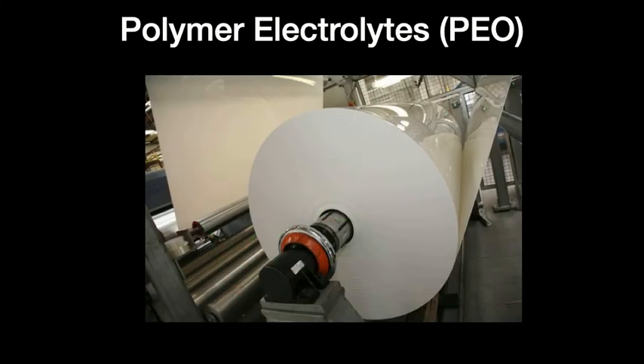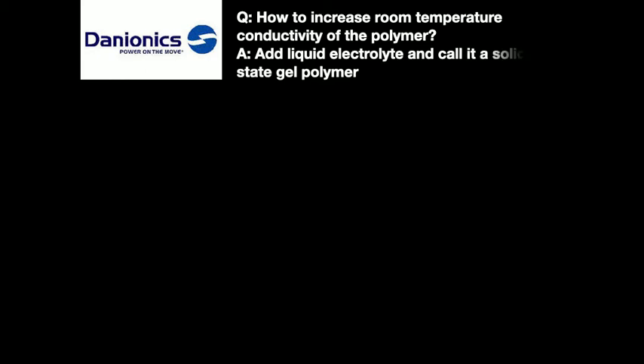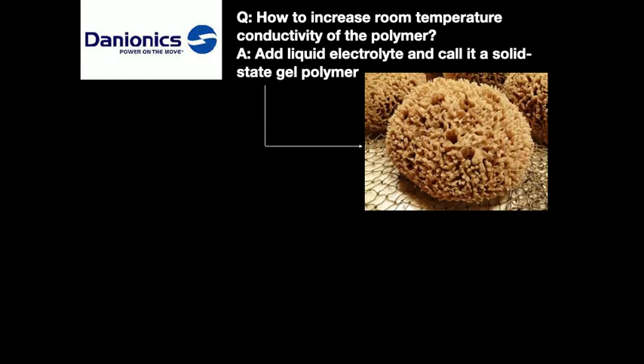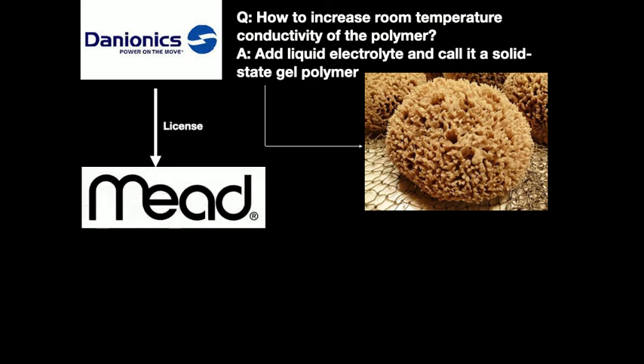Again, the advantage of polymers, though, is that you have this high-speed roll-to-roll processing, so you should be able to reach parity with lithium ion, and that's certainly an advantage. There have been companies that have commercialized room temperature polymer electrolyte batteries, but they took the approach I mentioned earlier. They addressed this issue of how do you get to room temperature if you have a polymeric electrolyte? Well, they added liquid, effectively making a gel. So you kind of have a sponge with liquid electrolyte in that sponge.